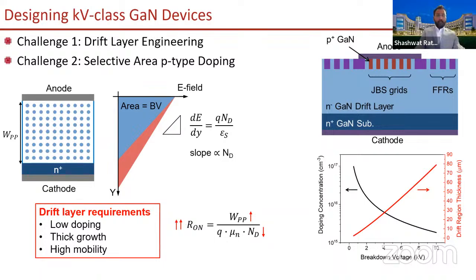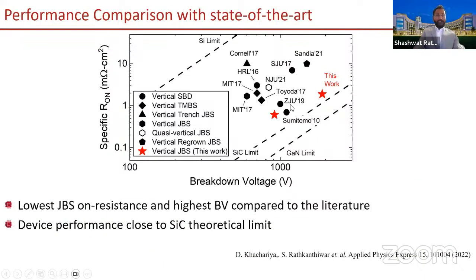We worked on this technology for many years, and I'm going to show you the final result. We got this project from the Department of Defense here in the US. We eventually delivered this product, where in our on resistance versus breakdown voltage, you can see that we delivered a device which was one of the best devices out there, which had for a given breakdown voltage one of the least on resistances. So much so that the devices are already close to the silicon carbide theoretical limit. Silicon carbide is the existing technology right now, and even our prototype devices seem to be working quite optimally. So it shows a huge potential to replace the already developed silicon carbide technology.